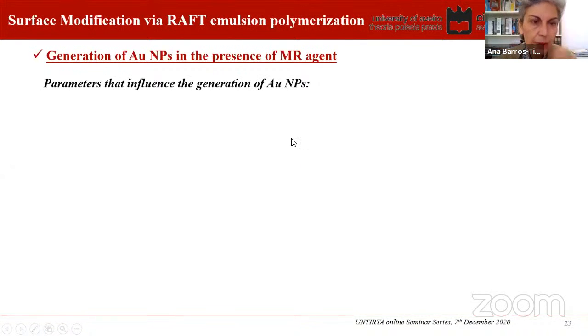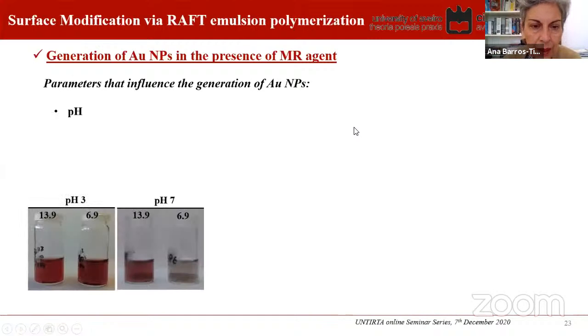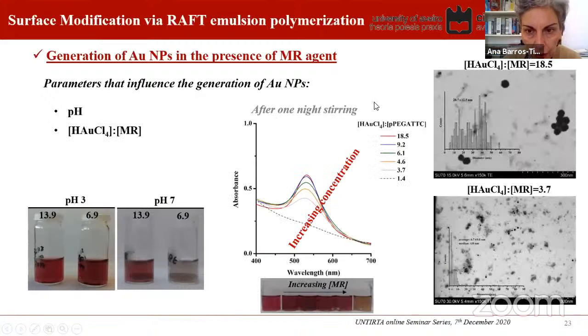As regards the formation of the gold nanoparticles in the presence of the macro RAFT agent, we had to, first of all, assess the influence of the parameters that determine the type and the quality of the gold nanoparticles prepared. First of all, one aspect was the effect of the pH. Also, the ratio between the gold precursor and the concentration of the macro RAFT, as well as the time, as I'll show in a few minutes.